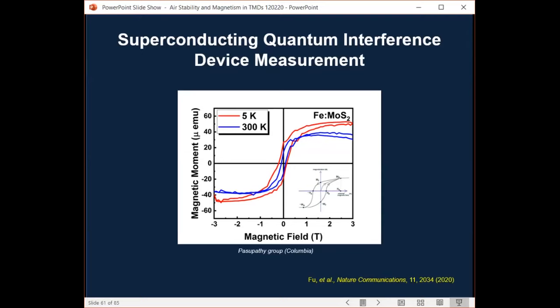The optically detected magnetic resonance spectra here, ODMR spectra here, show the energy splitting of 21 megahertz in the vicinity of the sample significantly larger than the undoped case. So undoped case 10 megahertz from the pseudo magnetic field and this case is 21 megahertz. So you have this huge energy splitting here, widening here. And this result further indicates the presence of local magnetic field because this was performed locally at room temperature. And the local magnetic field was also calculated to be 0.5 millitesla here at the room temperature. This is comparable to the values measured in 2D chromium triiodide at cryogenic temperature. We have also performed superconducting quantum interference device measurement or SQUID. And a lot of people also, a lot of review papers say that SQUID cannot be used to perform this because this is the signal would be too weak. But we have done this with Columbia University as well as our national lab and both cases we obtain all these results. So the difference from the previous measurement here is this SQUID measurement would measure on average the magnetic fields from the samples as opposed to local effect. So measuring this local and atomic level magnetization is important, right? Magnetic optical measurement is important, but at the same time measuring this average effect is equally important here. This measurement will complement the previous local magnetic field measurement here.